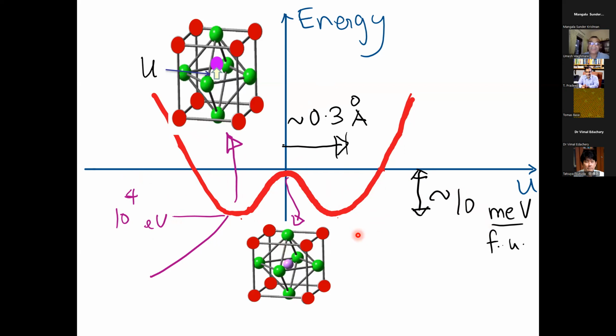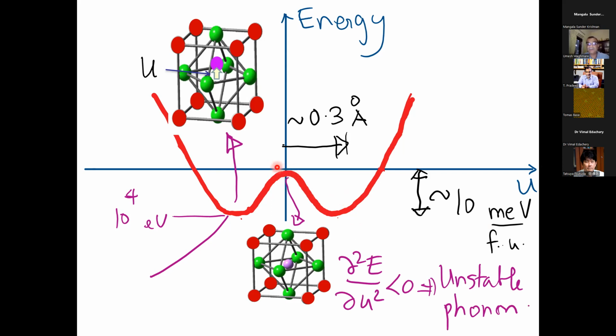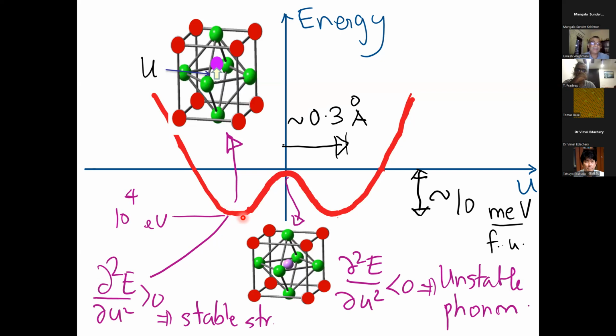Now I'm going to take this opportunity to explain another very fundamental aspect of these structural phase transitions, namely that in the high temperature phase, which is the cubic phase, the maximum of this energy well, since it's a local maximum, has a second derivative of energy with respect to U that is negative. And what this means is this cubic structure has an unstable phonon mode, because the second derivative is related to the spring constant of bonds, in this case, the off-centering of the titanium atom, and that results in unstable vibration at low temperatures. On the other hand, if at low temperature the crystal settles into this low energy phase, this energy here is a local minimum, and as a result, the second derivative of total energy is positive, and that means the structure is locally stable. So the key message is that vibration, or what we call phonon, is involved in this phase transition, and there is a concept of unstable phonon which I highlighted from this little cartoon picture.